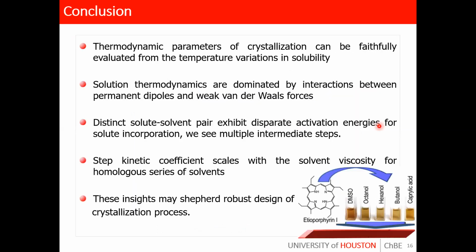So now we have looked into the effect of solute-solvent interactions on the thermodynamics, and we have understood how it affects the pathways of crystallization, whether it's direct incorporation or surface diffusion, and also the effect of solute-solvent interactions on the kinetics. So I would like to conclude by saying thermodynamic parameters of crystallization can be evaluated from the solubility variation in temperature, and for our tested pairs of solute and solvent, the interactions are dominated by permanent dipoles and weak van der Waals forces, as a result of which the solvent structuring at the crystal interface is negligible.